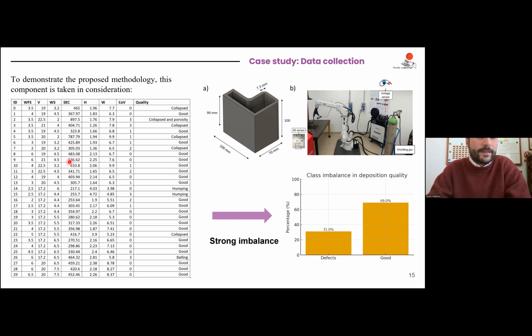Now, the problem is that at the end of the qualification procedure, you have a really strong imbalance. Of all the samples, every 1 second of deposition that you collected, 70% are related to good deposition data and just 30% to defects or anomalous conditions. So it's really hard to develop a supervised machine learning algorithm to do the process monitoring in this case.